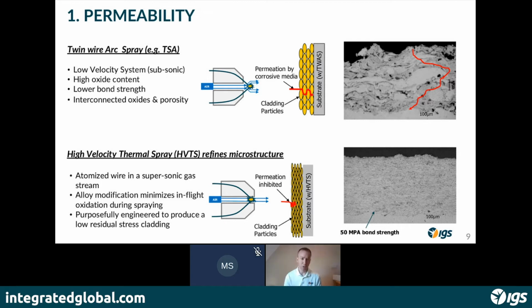And what we found was the particles were relatively large. They were relatively poorly configured in terms of the microstructure, and also that they had a large amount of porosity. And that meant that there was typically an easy pathway for the corrosive species to get to the substrate to cause breakdown. So the way we addressed this was to redesign the gun itself. So we brought the arcing point inside the gun, and we created a supersonic high velocity gas stream in that location.